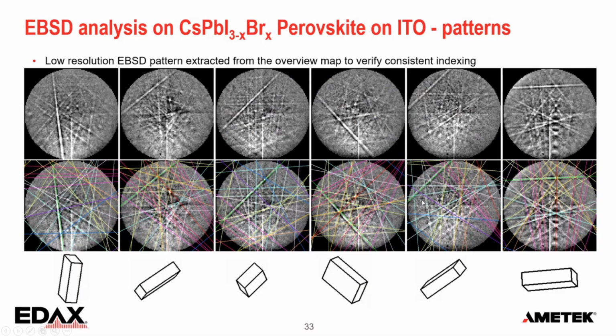And then I collect the map. I store all the patterns so I can do NPAR and everything I want to do later. And in most cases, I just move my mouse over the map offline just to see if I can grab a number of patterns. And in this case, it's very distinctive. There's one band that is very, very strong and the rest is a lot weaker. So we have a nice anchor for this indexing. It's this green band here that we can just make out that helps me to identify if the indexing was correct.